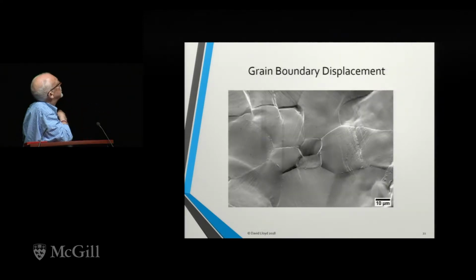This is another FIB image at a different magnification, and here is this grain boundary displacement. And this is really significant displacement. Now, you do see it in tensile samples, and Tony Rollett has done some work on this in tensile samples. We saw it first in significant amount when Mukesh Jain and I were doing hydraulic bulge tests. And it's all a result of the fact that these grains are unconstrained, and the strains involved in bending locally can be really quite high.